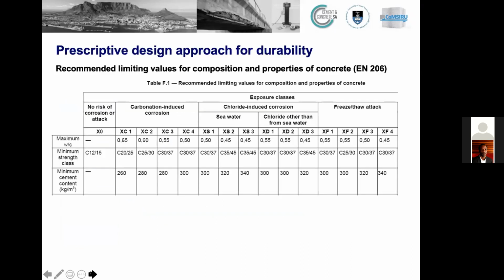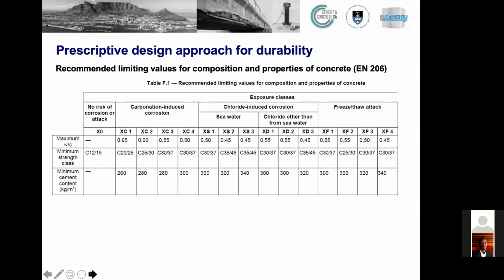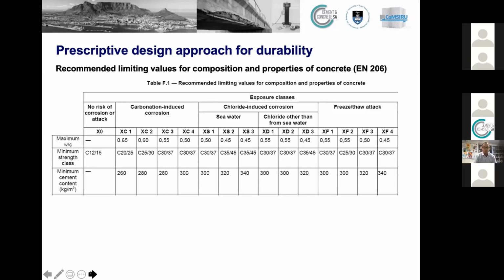And looking at these prescriptive requirements that we find in the Eurocode, which are also very similar to what we find in the current South African standards, you can see that for a certain exposure condition, this code gives limiting values for a maximum water cement ratio, minimum concrete strength, and minimum cement content. And essentially what this means is that the code assumes, or the designer is given the directive, that as long as these mix design parameters are met, the concrete will be durable in this particular environment.